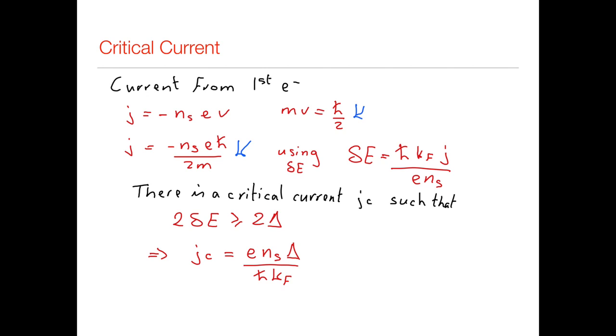Just as an example, for tin, at low temperatures, we have that Jc is of the order of 2 times 10 to the 11 amps per meter squared, just to give you an indication of that.